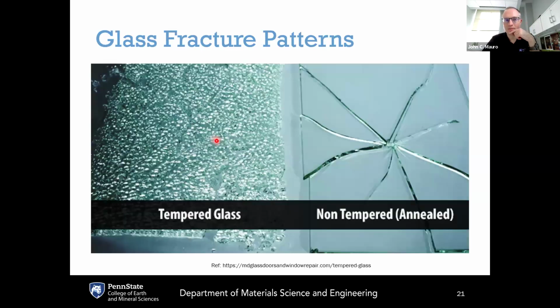You can have glass fracture following different patterns depending upon stresses that get released. If you have a non-tempered glass like an annealed glass, the cracks will propagate out in straight lines. So this is all the energy because of the initial impact, but the glass is not releasing any more tensile energy, and so you don't get any branching after the initial impact.